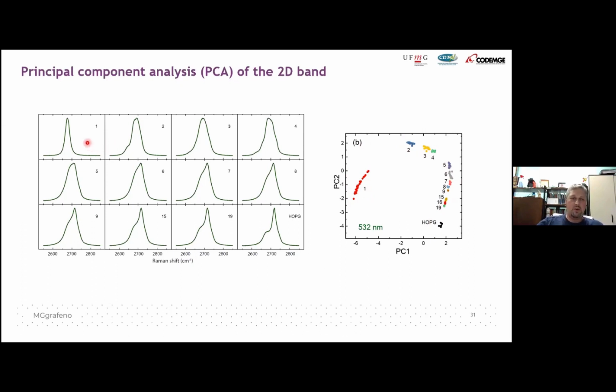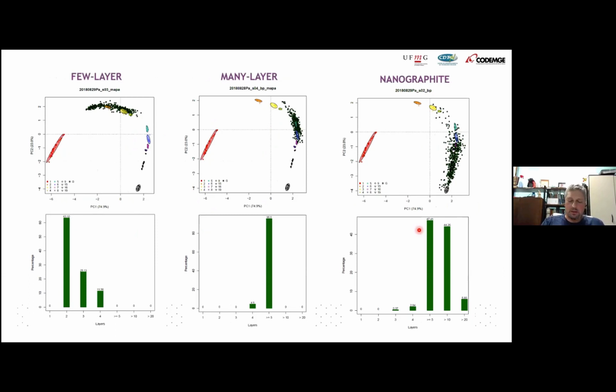The problem here is that our brain can differentiate these peaks very much, but it's not easy to make some sort of fitting procedure that makes clear, mathematically clear, what's 1, 2, or 3, or 4 here. So we use this PCA analysis and we build this standard space. And now we measure our graphene. The same samples that we measured with AFM, we do a Raman map, and we also measure thousands of Raman spectra. And we do the PCA analysis. We call it standardized PCA analysis because we project our graphene in our standard PCA space. And we see the distribution.